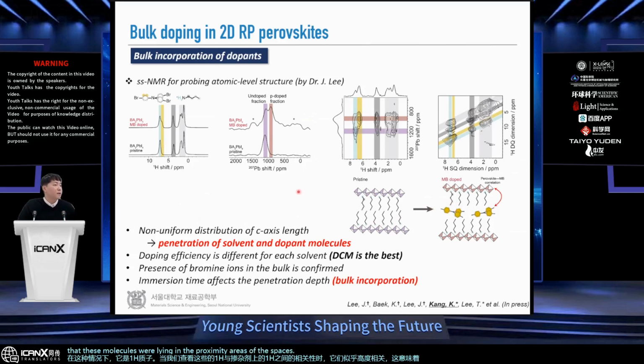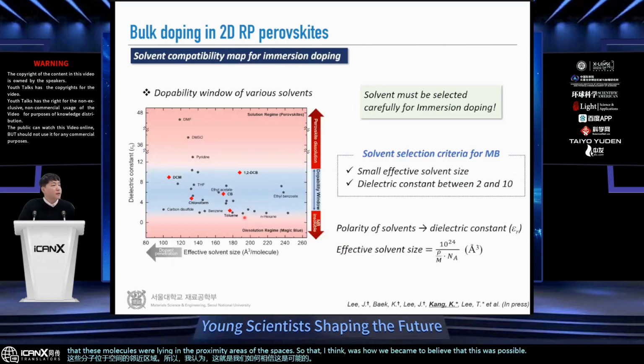So that, I think, was how we came to believe that this was bulk doping. And as I mentioned, the solubility as well as the effective solvent size had a good effect as well. So we'd like to call this a Goldilocks zone, where DCM, in this direction, the doping effect was the largest because it has the smallest solvent molecule size, as well as the right solubility of not dissolving perovskites.